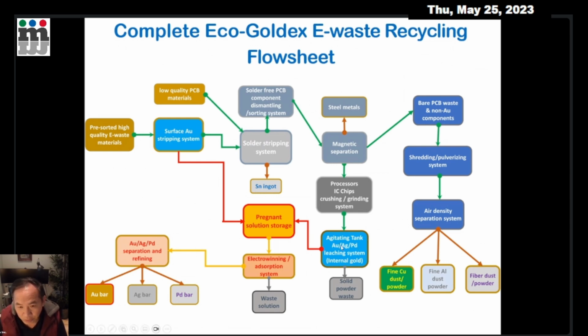And then we separate the powder from the pregnant solution. This pregnant solution will be sent back to the electrowinning to recover. So the electrowinning system is shared, either for solution from the surface gold stripping or the internal gold leaching solution. From here, you have only the solid powder waste. And for the bare PCB board, there's no component, only the board. The board contains many copper wires. This is how the PCB, printed circuit board, comes about. Printed wire, many copper plus plastic or epoxy. From there, we use a shredder or pulverizing system. Then we use air density separation to recover all the copper wire dust or chips and fine aluminum and fibers.